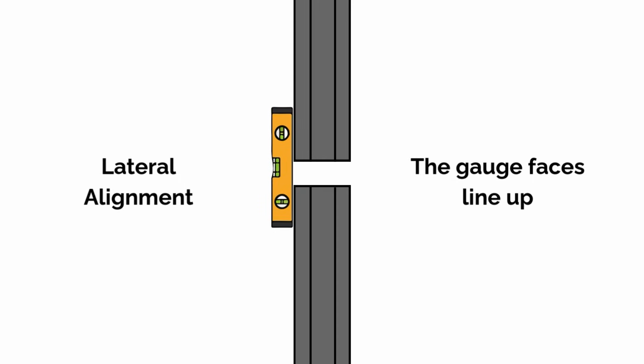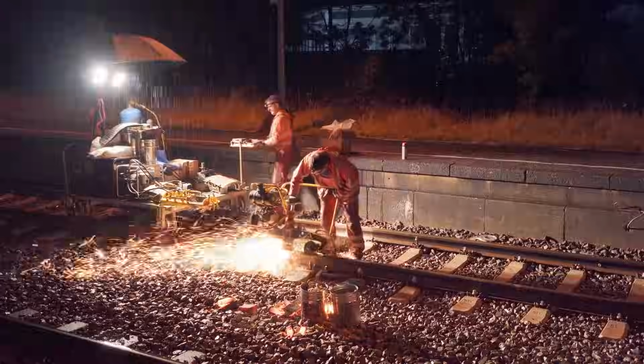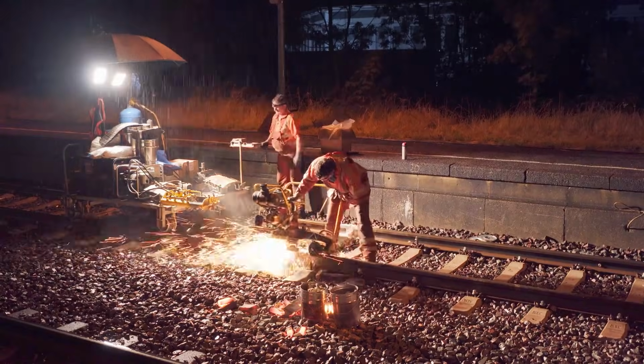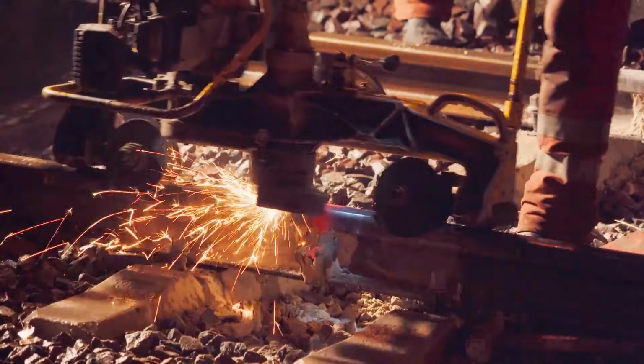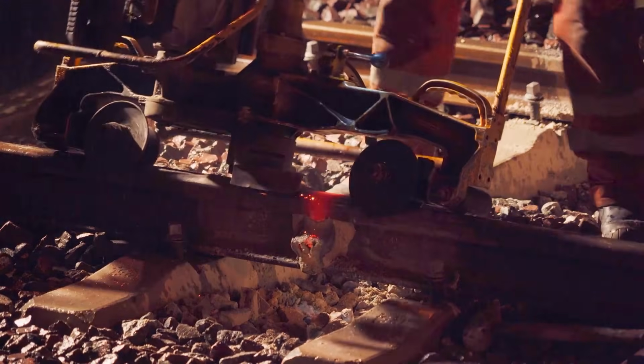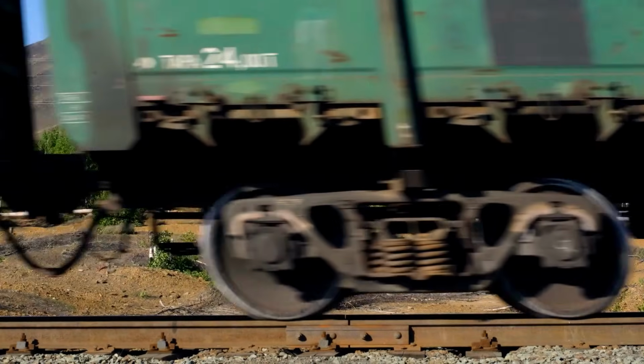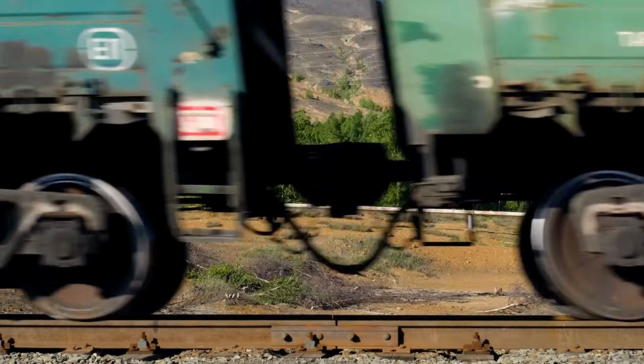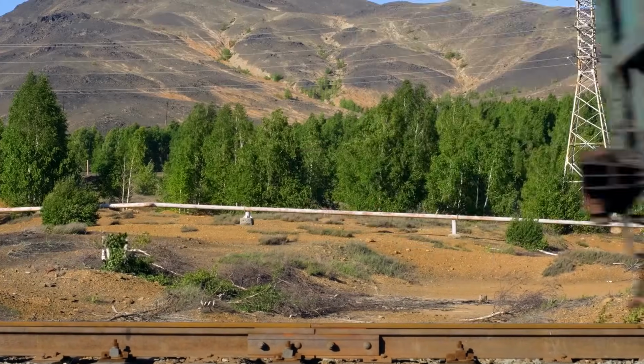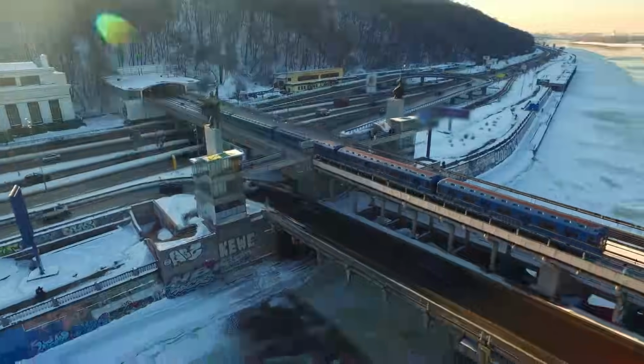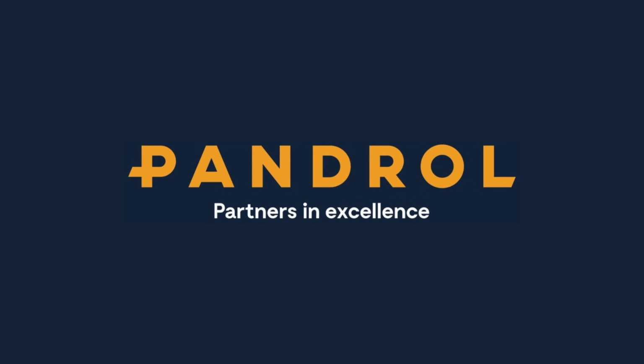Lateral alignment. The gauge faces line up across the joint. Longitudinal alignment. There's no step or kink through the joint. Once locked in, it must not move. Grinding later can refine the surface profile, but it can't fix misalignments inside the weld. That's why this stage decides whether the finished joint runs smoothly or hammers under every wheel for the rest of its life.